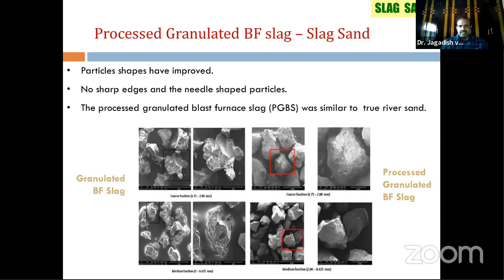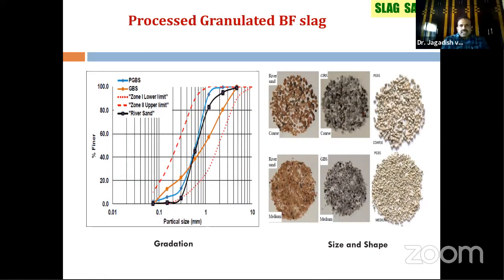You can see here the microscopic pictures. These pictures were taken from the JSW plant. And even the gradation, when you compare river sand with granulated blast furnace slag and processed granulated blast furnace slag, the size and shape parameters improved, and the processed granulated blast furnace slag gradation curve matches with the natural river sand gradation curve.